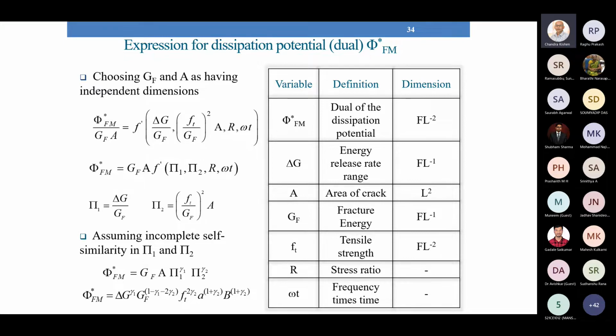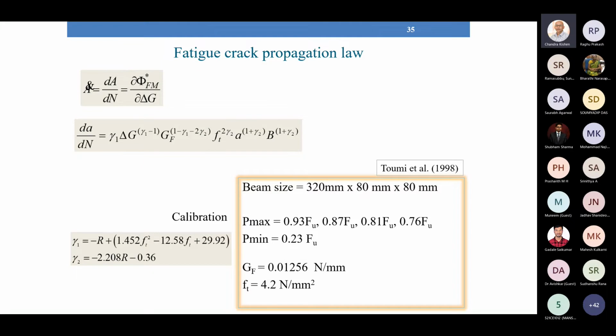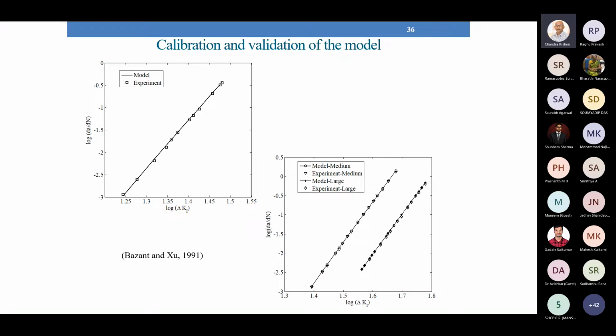From this potential, we can obtain the rate of crack propagation. Now there are two constants here which are determined through calibration of some experimental results, which we have done here and obtained this. So this is a calibration. We have calibrated this